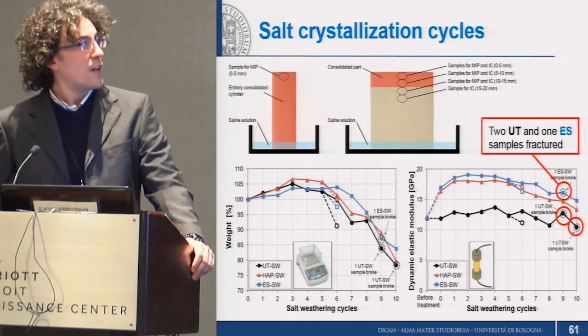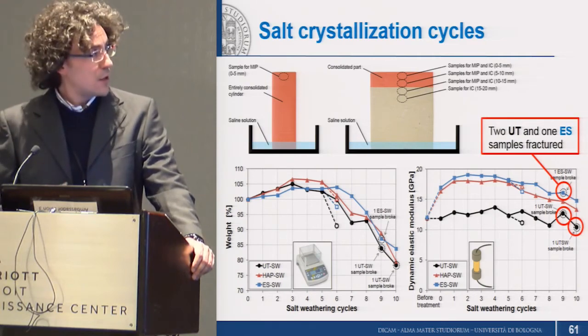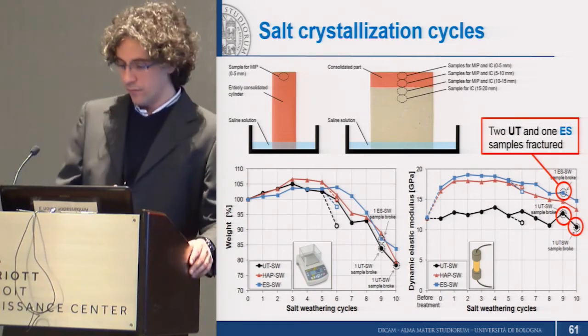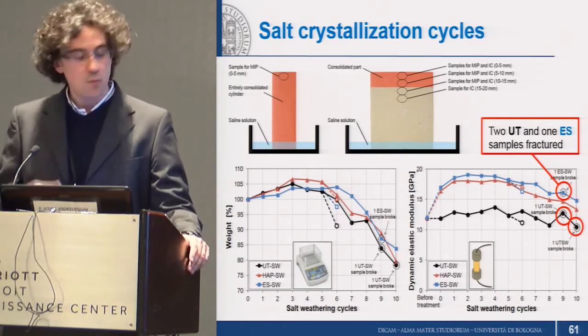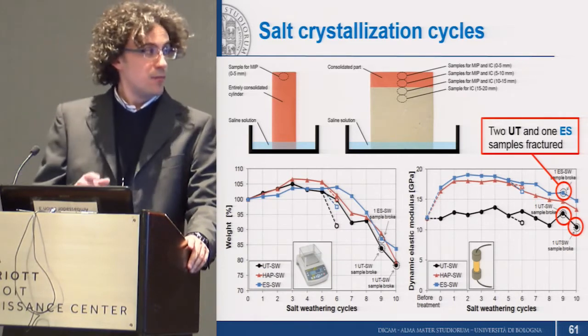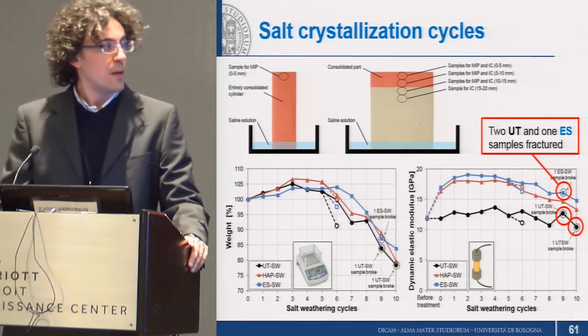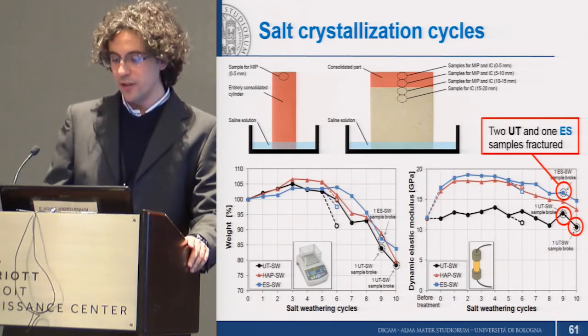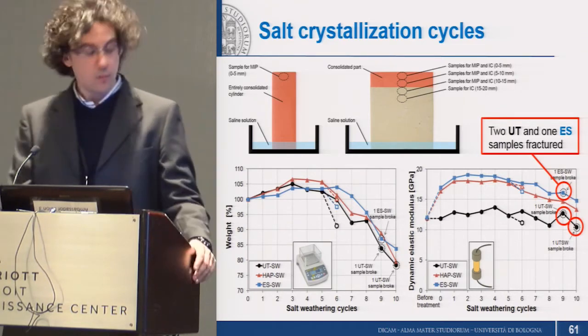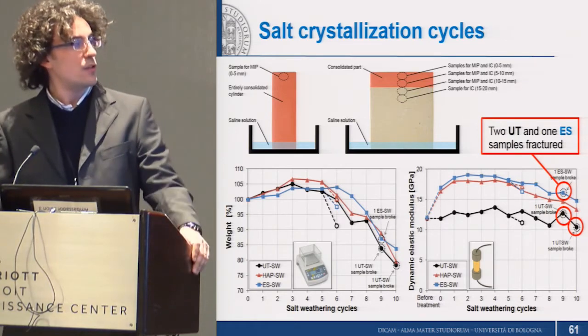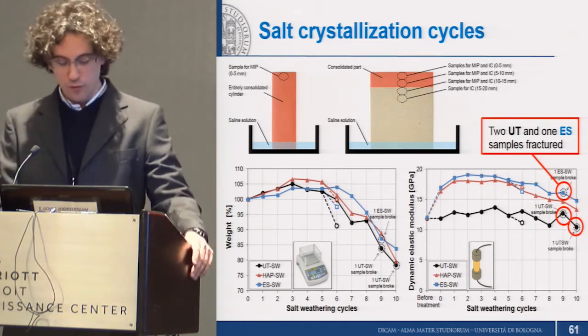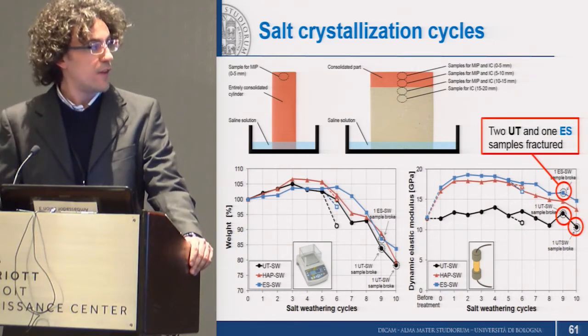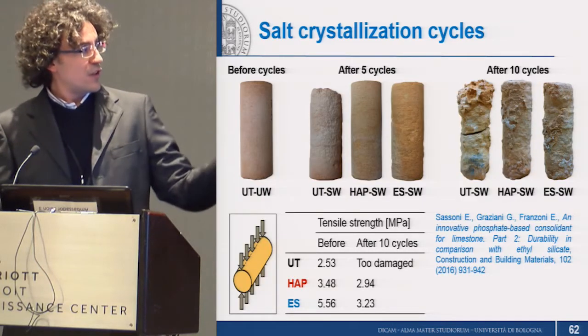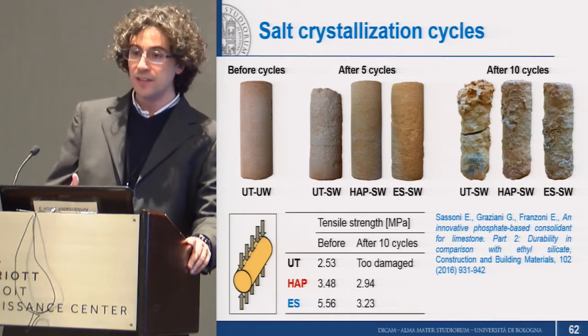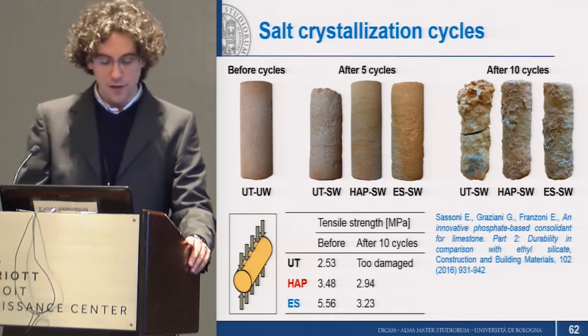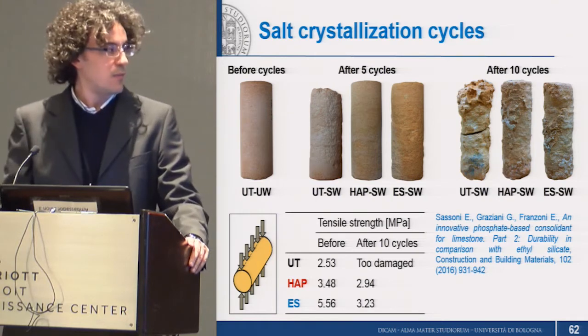So we carried out some sodium sulfate crystallization resistance cycles. As you can see on the right, 2 untreated samples and 1 sample treated with this other alternative consolidant failed over the cycles, while samples treated by our treatments were able to reach the end of the cycle without fracturing. And also, again, in terms of mechanical improvements, such as increasing tensile strength, the initial benefit of this alternative consolidant is basically lost.